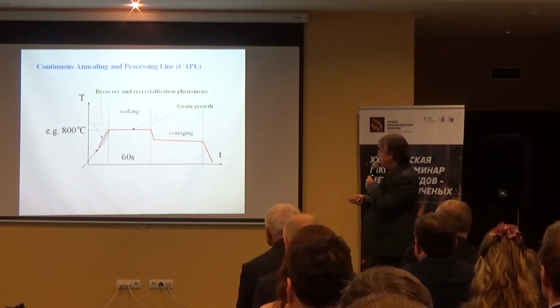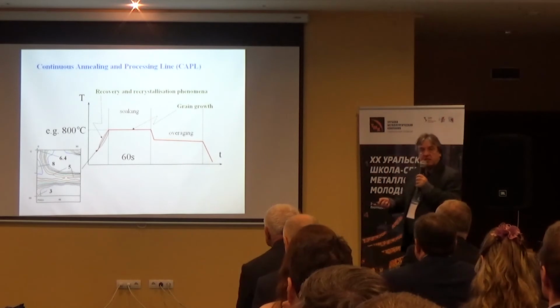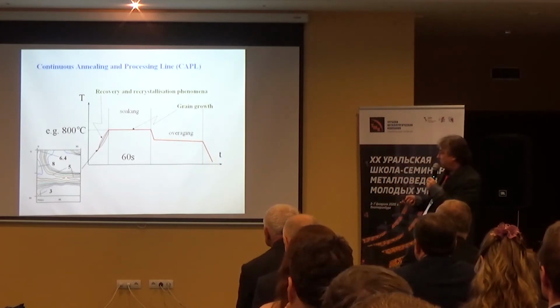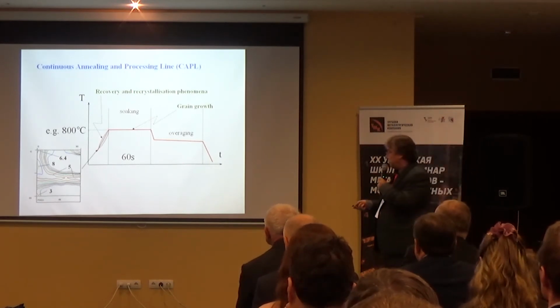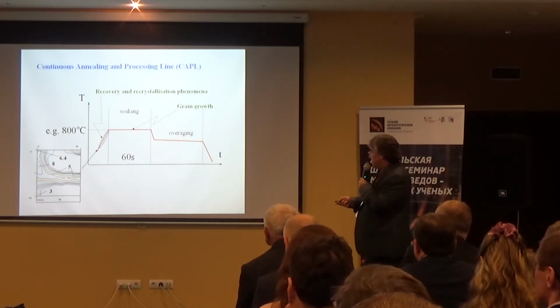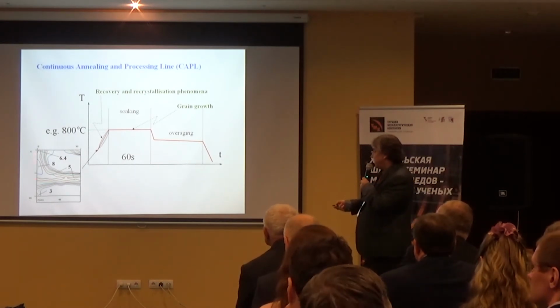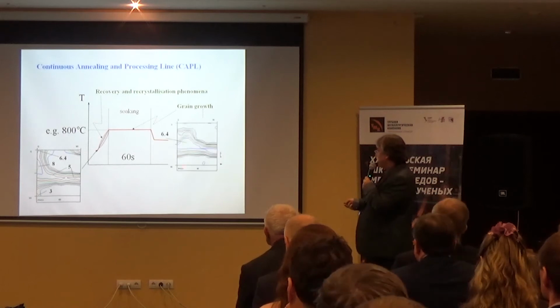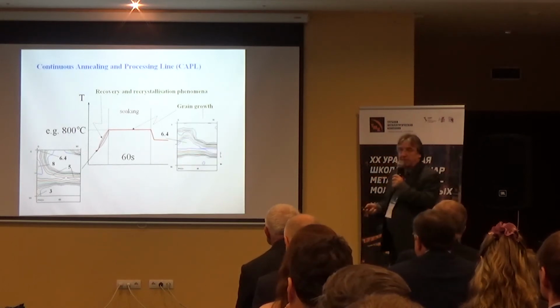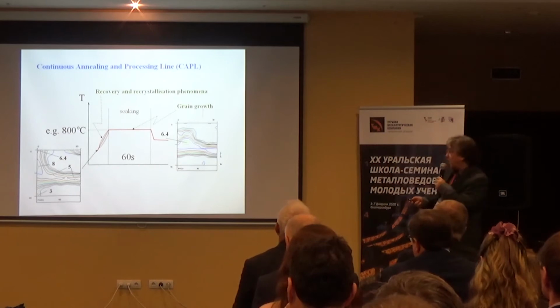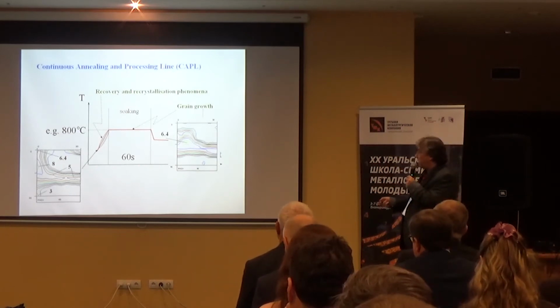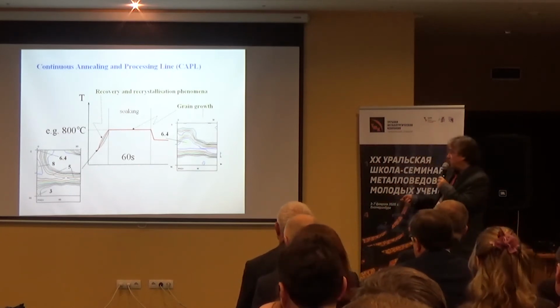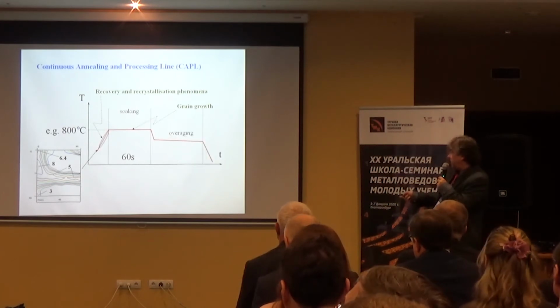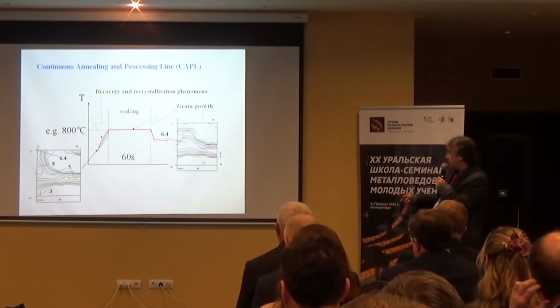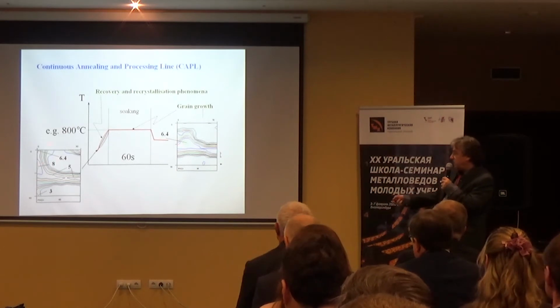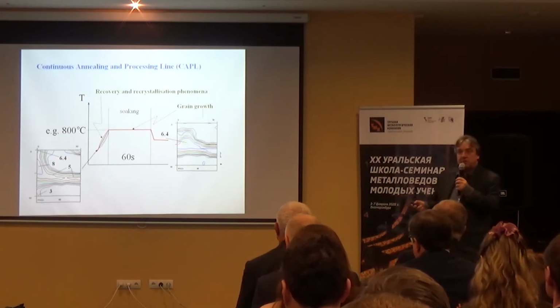Now, normally we also have recrystallization if you deal with low carbon steels, and then during recrystallization you get the transformation of the alpha gamma fiber texture typically to a gamma fiber texture. So this is the result of recrystallization and grain growth. So now we basically have the gamma fiber. So here we had the alpha gamma fiber, now we have the gamma fiber.